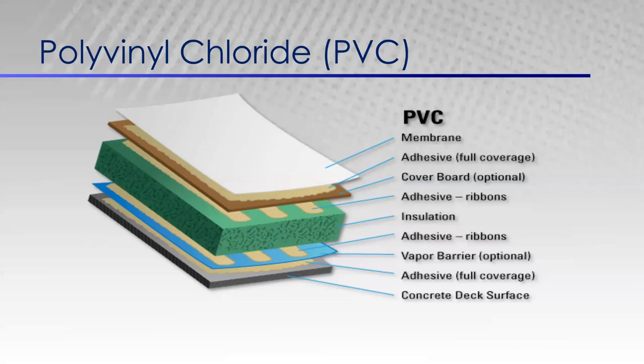That standard was published in 1985, and it has had several revisions ever since as we continue to grow our uses for PVC. PVC vinyl roof membranes can be produced by a number of methods, whether it's a strike-through process, extrusion, calendaring, or laminating. It can be a combination of both. But what you'll find is a finished PVC membrane that is supported by either polyester or fiberglass reinforcement. It also contains vinyl resins, ultraviolet light inhibitors, heat stabilizers, biocides, pigments, and plasticizers.